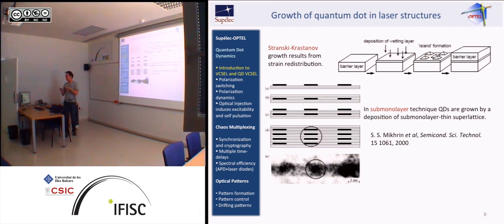So those people said, okay, let us do it. They grew things that were not lattice matched, and if you put a layer that is not lattice matched to another one, you have some strain, and apparently some redistribution of the strain can end up in the natural and spontaneous formation of islands that will in fact play the role of the quantum dots. I mean, they will play the role of 2D confinement and then quantum dot-like properties.